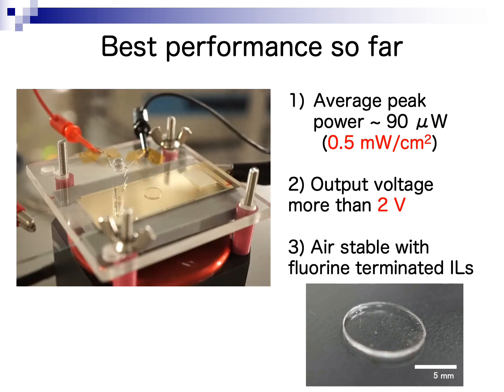Finally, we are going to show the best performance so far. The average peak power is around 90 microwatt, and it is around 0.5 milliwatt per square centimeter. So it means that if we enlarge the size of the electret, we can get more power.